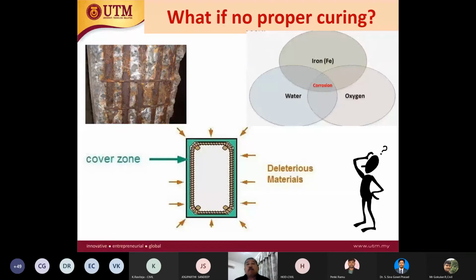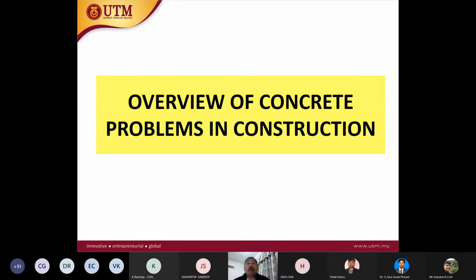All right. So if we don't do proper curing, the concrete cover becomes porous because there is less CSH gel, because part of the moisture will be lost from here. Once the concrete is porous, oxygen and water can penetrate, reaching the steel, and then corrosion starts to occur. So that is the concept. Okay, so we need proper curing.